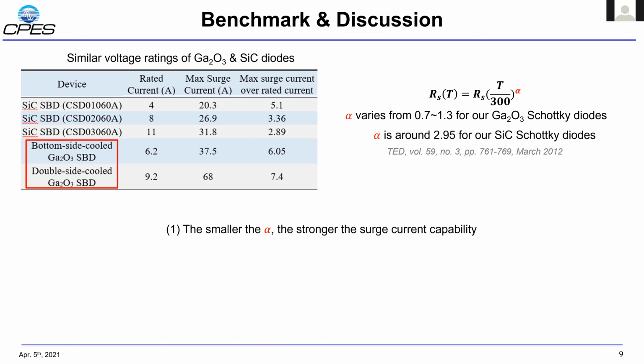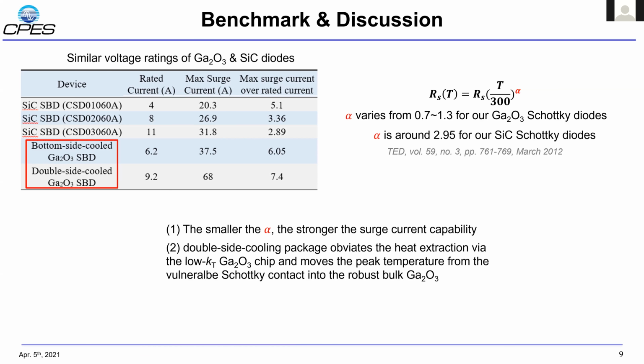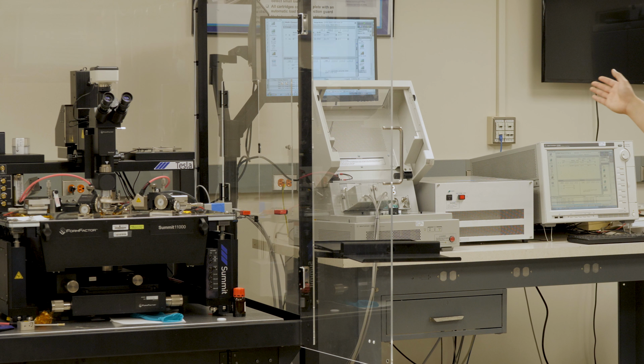surge current capability is. And the second reason is that the double side cooling package obviates the heat extraction via the low thermal conductivity gallium oxide chip and moves the peak temperature from the vulnerable Schottky contact into the robust bulk gallium oxide. Now we're going to measure a double-side cooling packaged gallium oxide Schottky barrier diode with silicone gel protection.